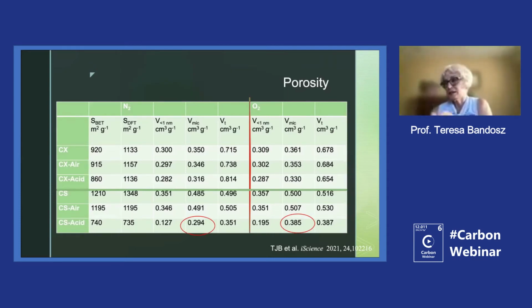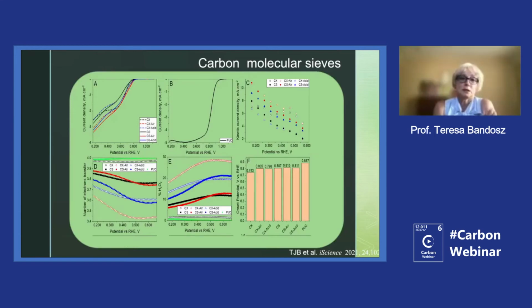Of course, the question is whether it is really a volume or just related to more oxygen interacting with the surface. So here are the results of the electrochemical test, and it is interesting because Cx you can see as a dotted line and Cs as the solid line. What happened after modification, especially of Cs? We increased the kinetic current, and those two sieves have different shapes of the LSV curve. And if we look at the number of electron transfer, you can see that the best, and very close to Pt/C, is Cx. And then the two others are Cs and Cs oxidized.